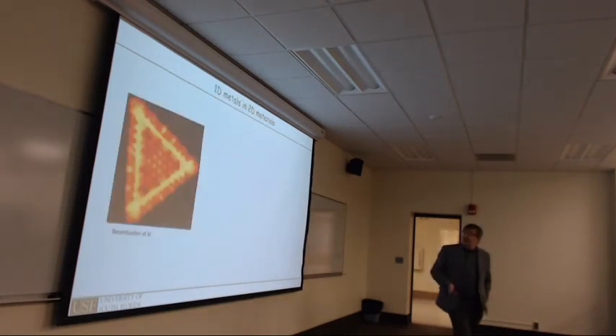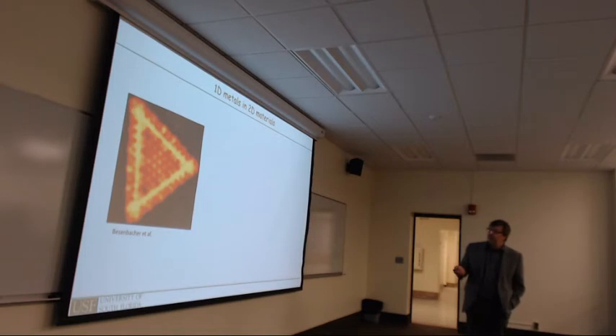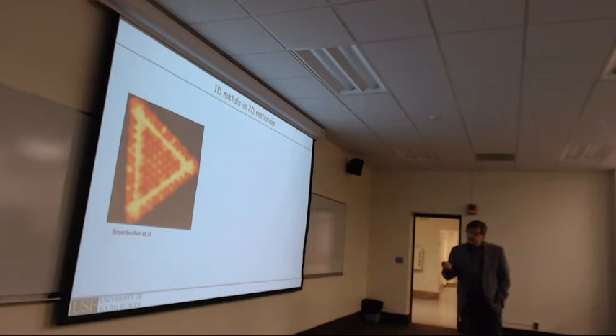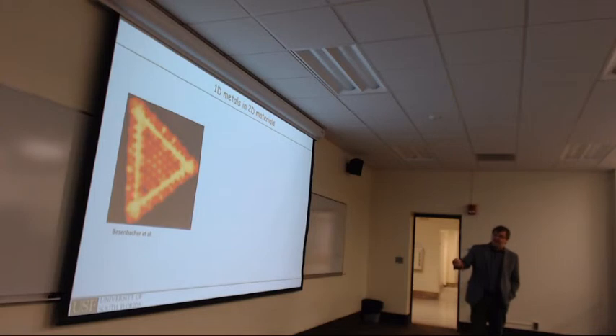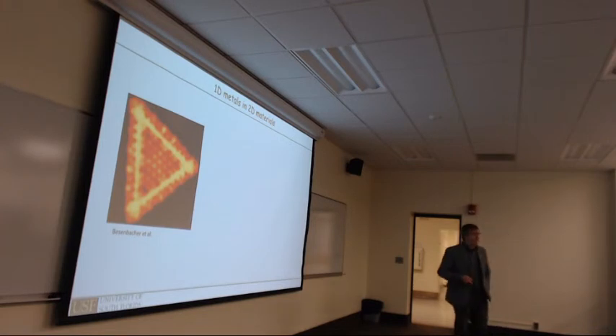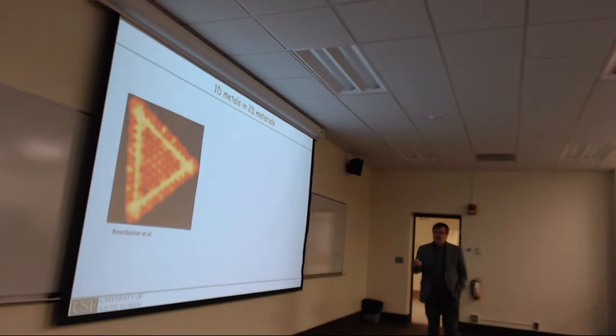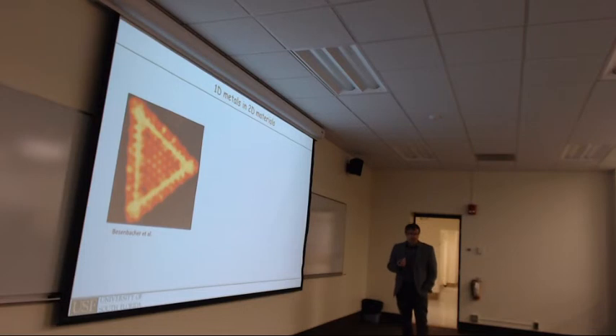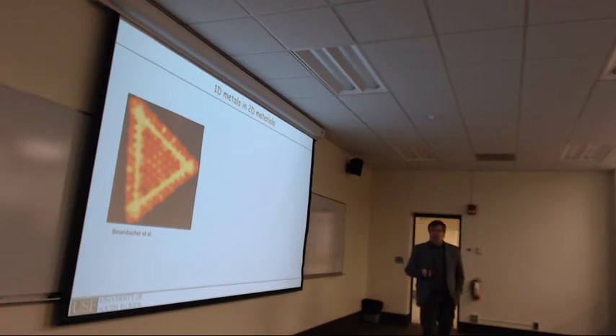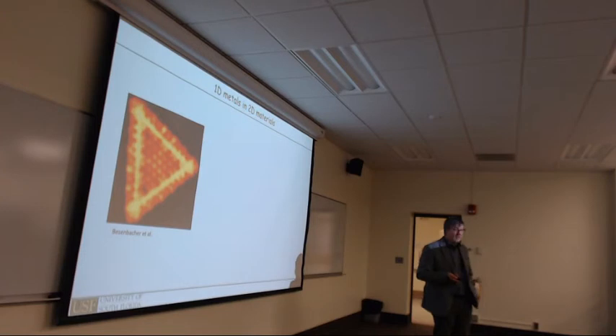Right. So anyway, an old famous example is molybdenum disulfide, here from the Besenbacher group, grown on gold. And so if you have these little islands, so this atomic corrugation of molybdenum disulfide, what they recognized is that the edges of the molybdenum disulfide islands become metallic. The molybdenum disulfide is a semiconductor, and you have the edges as metallic. They proposed that this contributes a lot to the chemical properties, chemical reactivity of molybdenum disulfide, for example, hydrodesulfurization reactions.